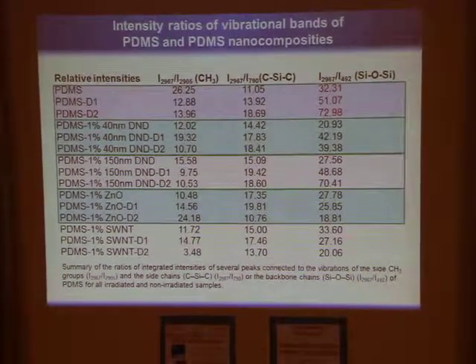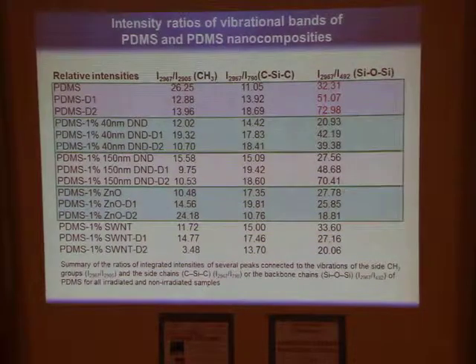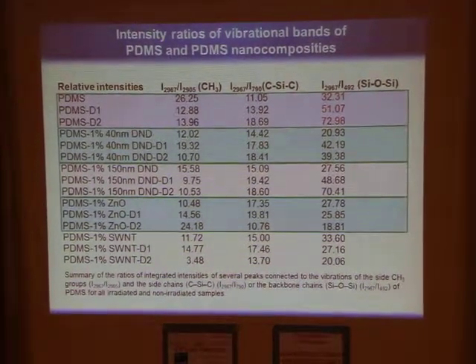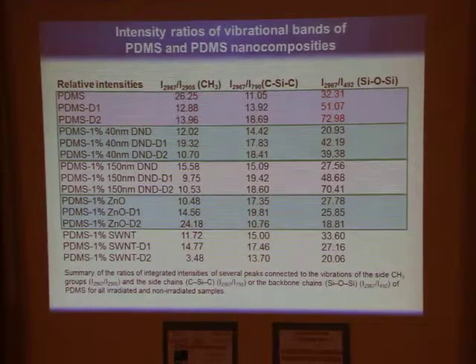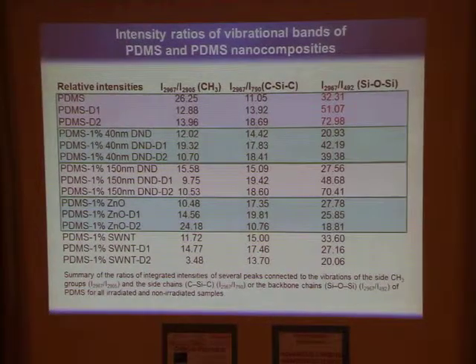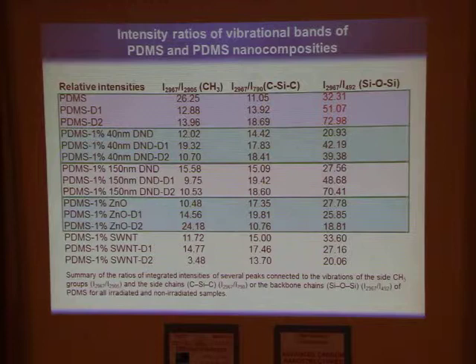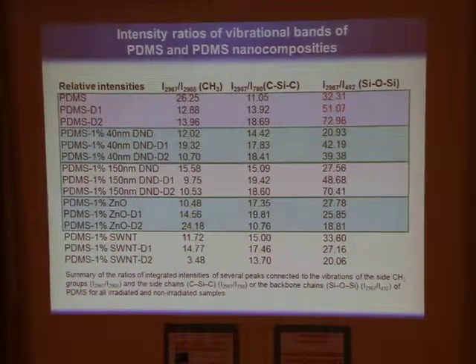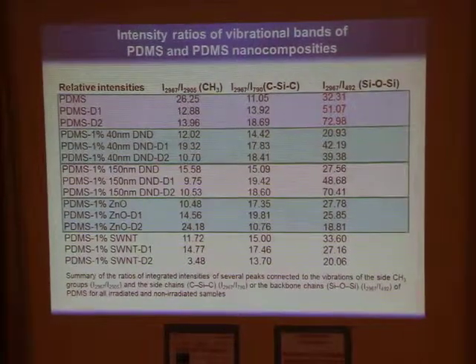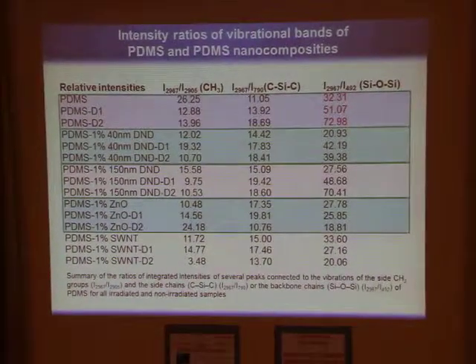And zinc oxide and single wall nanotube show a more significant improvement in stability of the backbone bond as compared to pure PDMS. So in general, 150 nanometer nanodiamond is not as useful for these composites as small particles of nanodiamond and zinc oxide, as well as nanotube, for low doses.